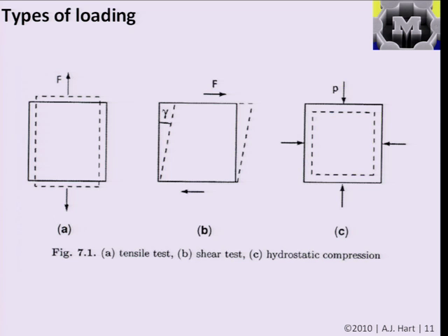and also cases where you're applying, for example, uniform or hydrostatic pressure or bulk compression to the material. And we saw in one of our first lectures that because of the surface pressure, the effective surface energy, because of the dangling bonds around the surface of a nanoparticle, there's actually a very high internal pressure in a nanostructure. And this can change the lattice spacing, or the spacing between the atoms. We had a plot from experiments where we saw that for gold nanoparticles. And remember, the change was really small, but it could still be measured using X-ray techniques that precisely measure the spacing of the structure.